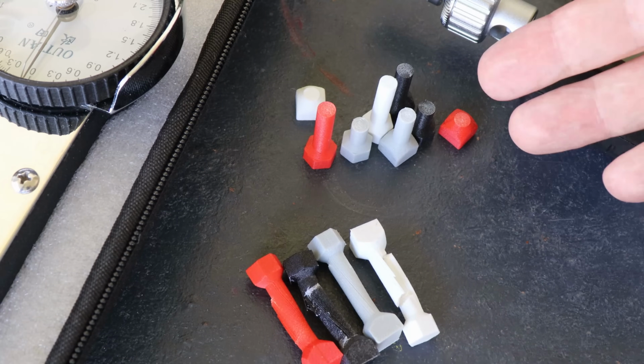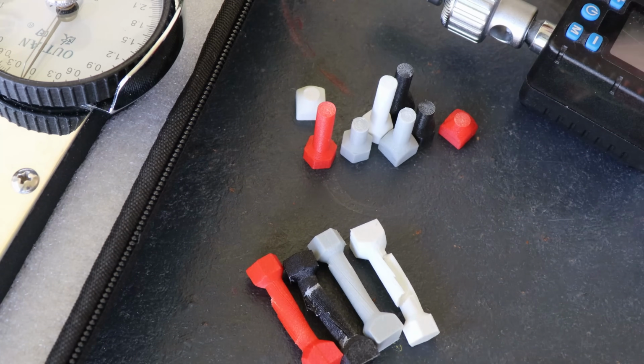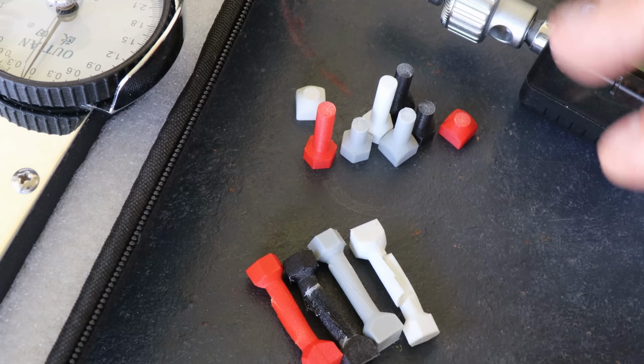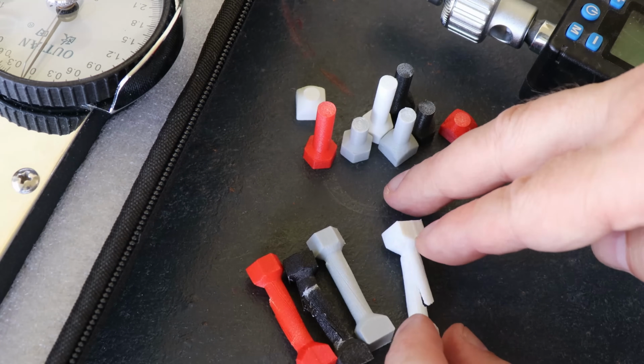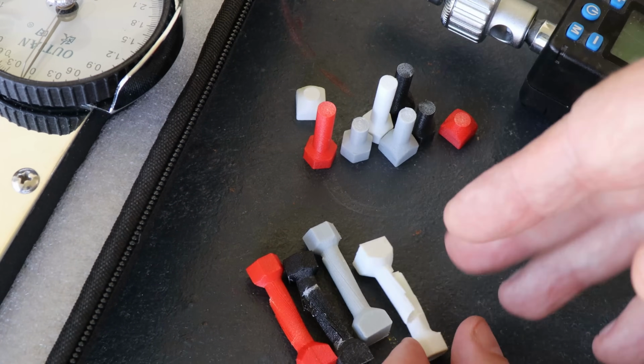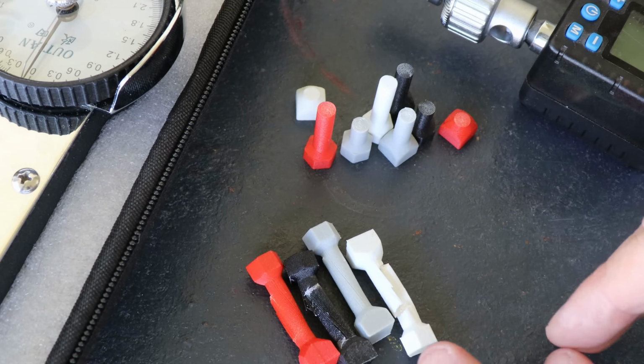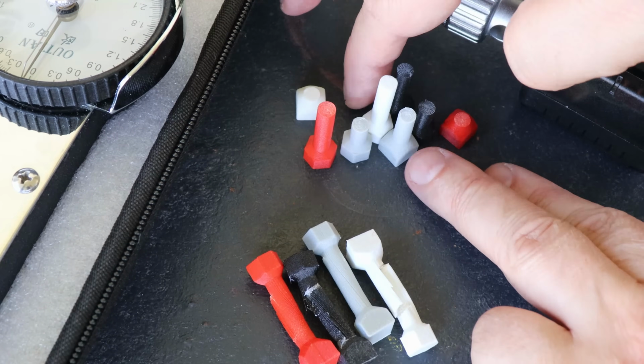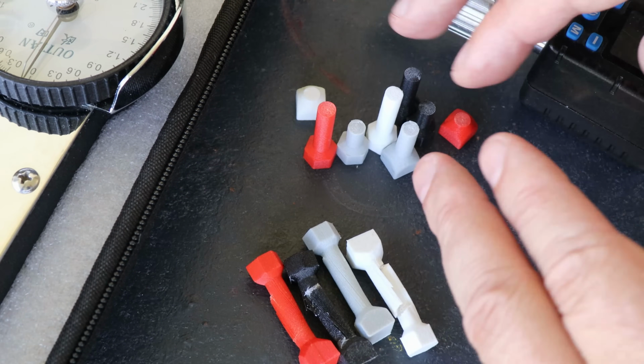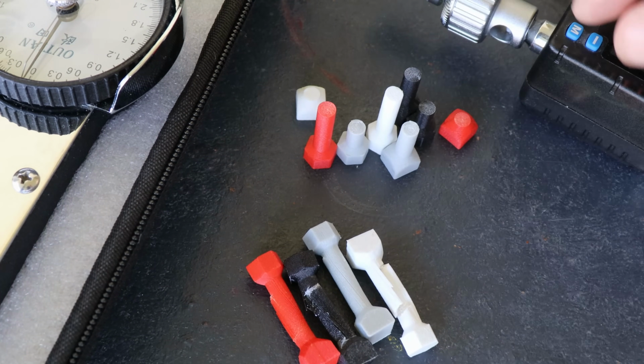Now this was interesting. As you can see, very similar numbers, similar break loads, but they broke completely differently. Those printed in horizontal position can twist a little bit. In this case, only a 90 degree angle, but sometimes I can do much more. Those printed in vertical position broke on similar loads, but more suddenly.